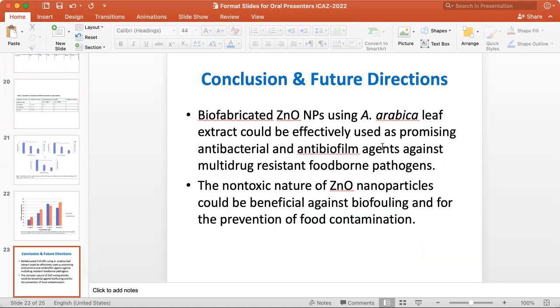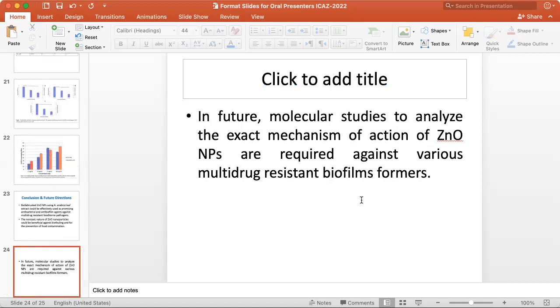So we can conclude that these nanoparticles that were synthesized by using a green approach act as promising antibacterial and antibiofilm agents against foodborne pathogens. And these nanoparticles were also non-toxic. Results have not been shown here, but we have performed toxicity assays that prove that these nanoparticles are non-toxic to humans, as tested on a human cell line.